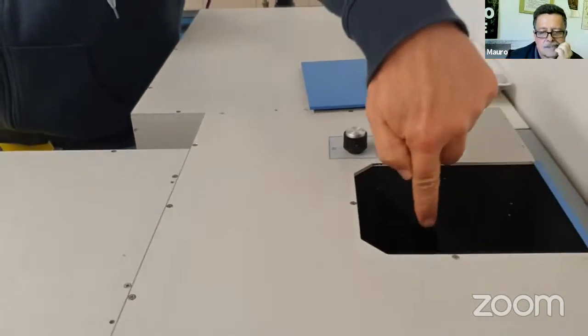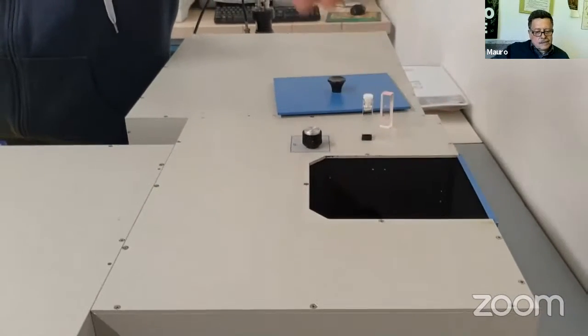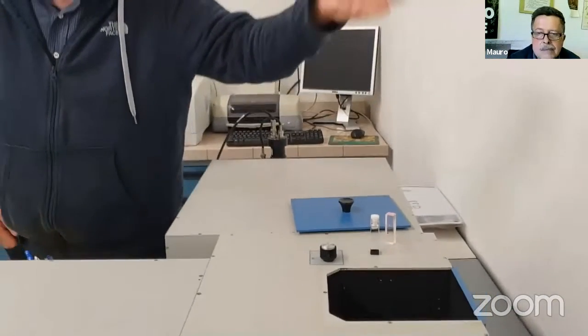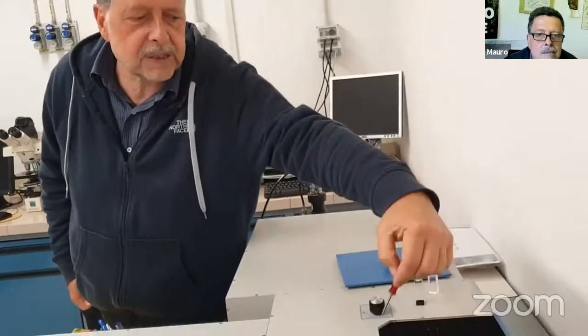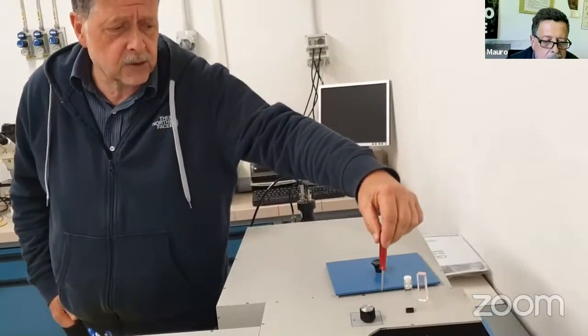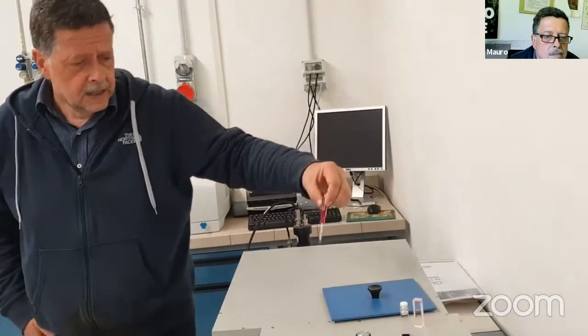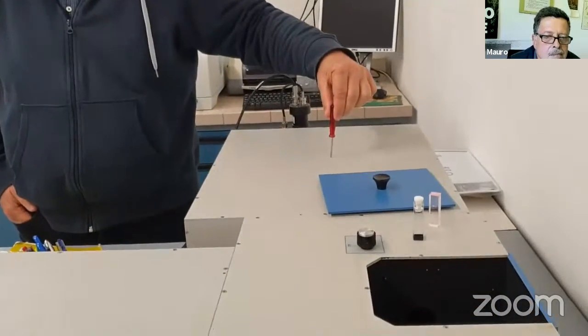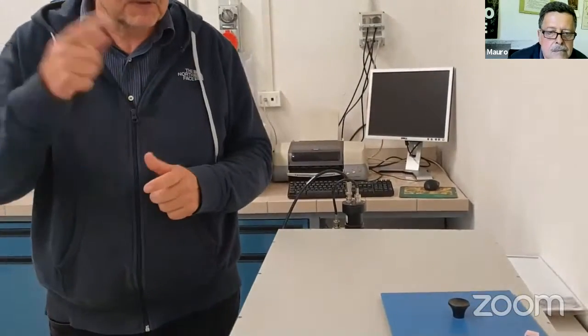So when the sample receives the lamp light, it can absorb the lamp light, and then this absorbed energy can be given back by luminescence emission. So the sample is supposed to emit luminescence. The luminescence is collected by a system of mirrors and sent to another monochromator. In this way you can analyze the spectral content of the emitted luminescence, and then there is a detector that gives the signal as a function of the emission wavelength. Okay.